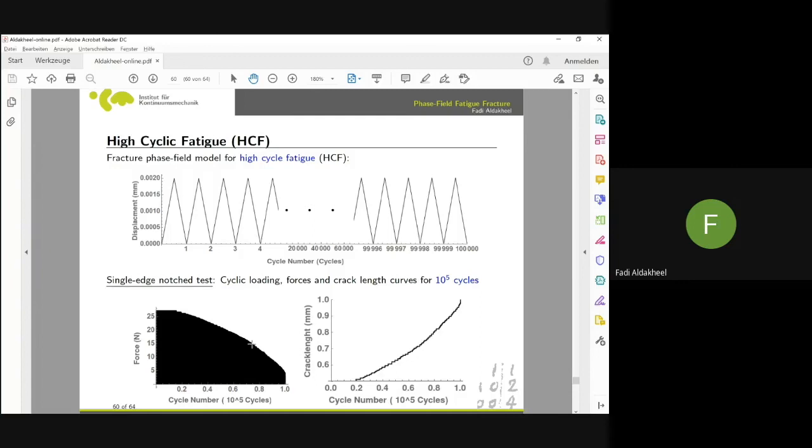Remember, we said that the model is under cyclic loading or under monotonic loading. It has been shown that wet concrete, or concrete underwater, experiences early damage behavior compared to the dry one, but in fact it's drastic if you are under cyclic loading. Normally, for an offshore turbine, the base is underwater, and the seawater is every day coming and going, right? You have a huge cyclic loading at each cycle. Due to that, they have seen experimentally a huge difference between dry and wet concrete due to the influence of water. They say it is really drastically decreasing the fracture toughness.